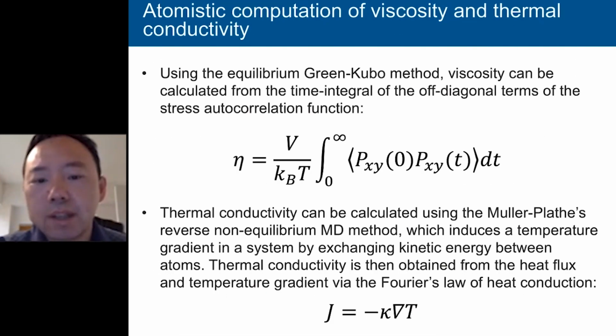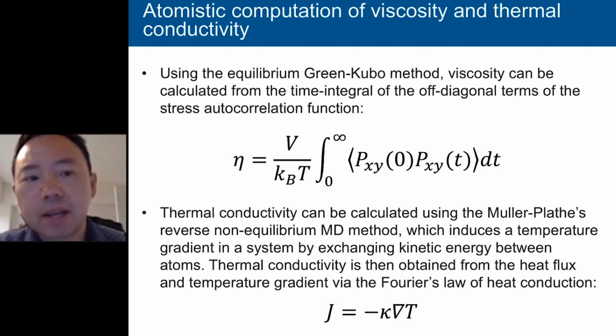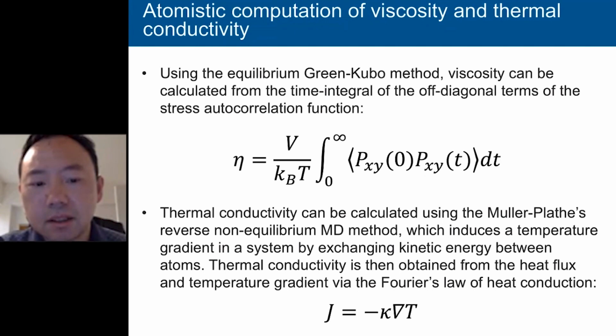This slide shows the equations we use to calculate the viscosity and thermal conductivities. For the viscosity, we rely on the so-called equilibrium Green-Kubo method. Essentially, the viscosity can be calculated from the time integral of the stress autocorrelation function shown in the integral. And the thermal conductivity can be calculated using the non-equilibrium MD method, which introduces a temperature gradient inside a salt by forcing some exchange of kinetic energy between neighboring atoms. And then the thermal conductivity can be calculated from the well-known Fourier's law of heat conduction. Essentially, it's the heat flux divided by the temperature gradient.